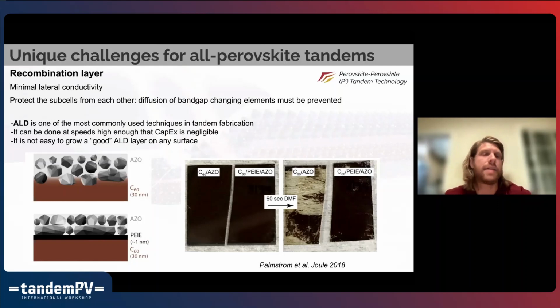And the recombination layer is a critical piece in that puzzle. I just have a note here that ALD is commonly used for this, and that's what you see in the literature. People like to criticize ALD for being an extremely slow process, and that can be true, but it can also be quite a fast process. It's used now in silicon cell manufacturing lines to passivate the contacts, and it can be done at speeds high enough that capex is negligible. There are also new solutions where it can be roll to roll, or sheet to sheet. There's a lot of exciting progress in that area, and we've had some good results on that as well.